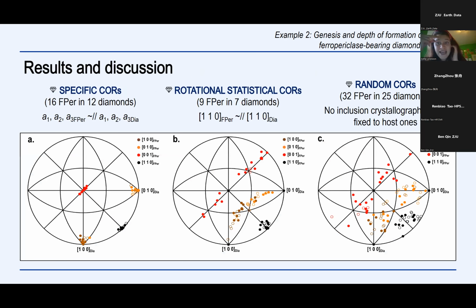Starting from the data that we obtained about the crystallographic orientation relationships, we observed that ferropericlases and diamonds can develop different types of orientations. Some are specific orientations, and this means that the three main crystallographic axes of diamonds are oriented with the three main crystallographic axes of the ferropericlases. In some cases, ferropericlases can develop rotational statistical orientations, and this means that one crystallographic axis of diamond is fixed to one crystallographic axis of ferropericlase. And finally, in some cases, ferropericlases can show random orientations, and it means that no crystallographic axis of ferropericlase is oriented with any crystallographic axis of the diamond.